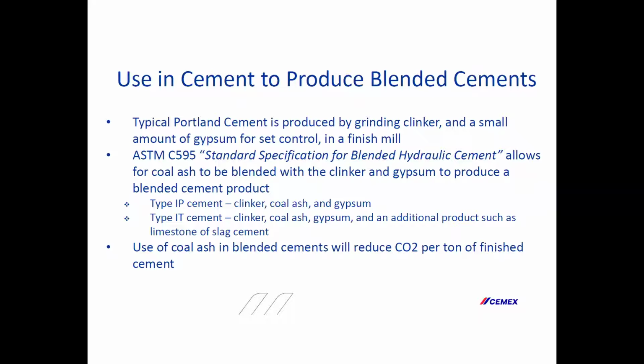Now, another use for these products that we are starting to see more and more of is blended cements. Cements historically are just Portland cements, which were just clinker from the kiln, gypsum, and you grind them in a finish mill. As Danny mentioned, we're starting to add limestone in it to produce Portland limestone cements. But there's also some other blended cement options that are allowed in the C595 standard specification for blended cements. We can take basically cement and fly ash and blend it, grind it in our finish mill, and produce a finished product that contains both the clinker or the cement and the pozzolan. And that would be classified as a type 1P cement.